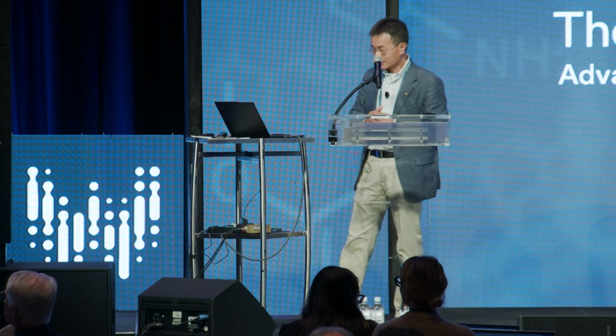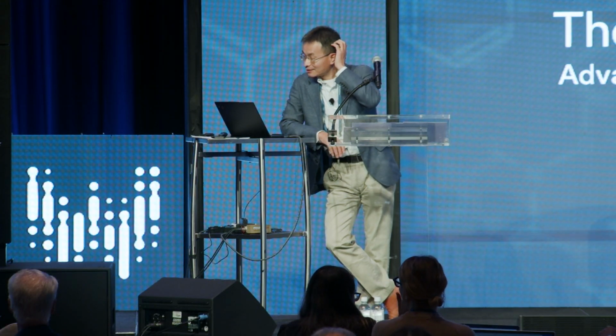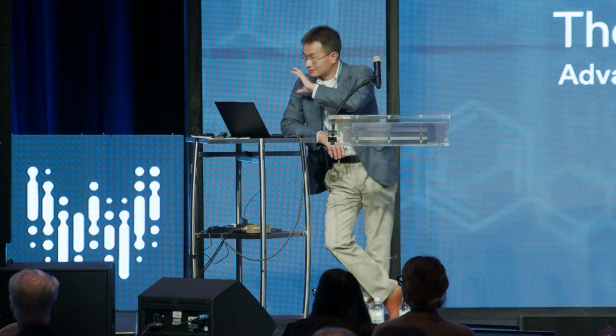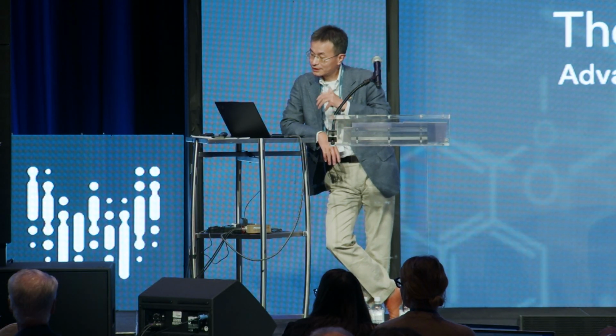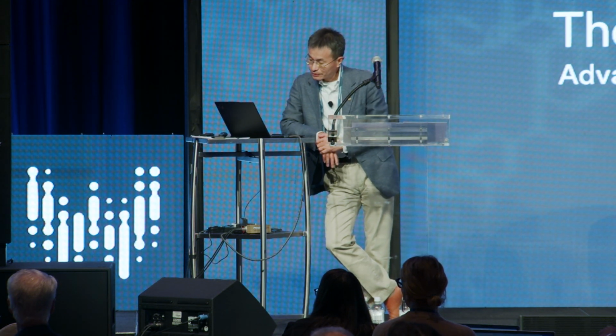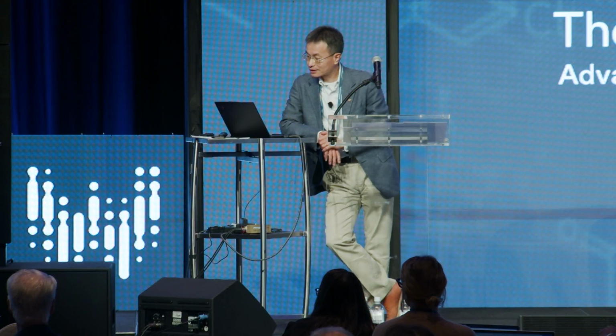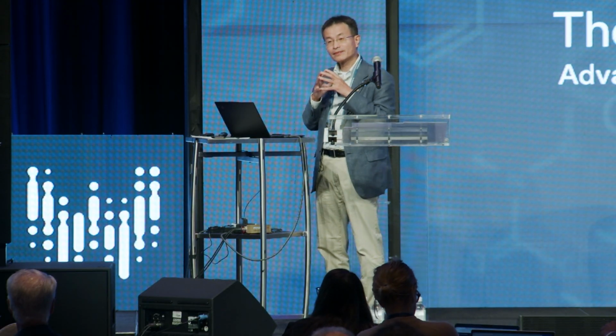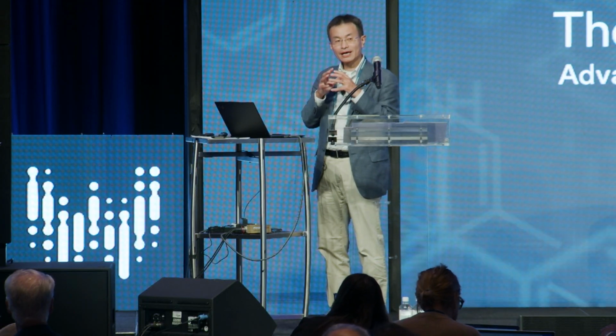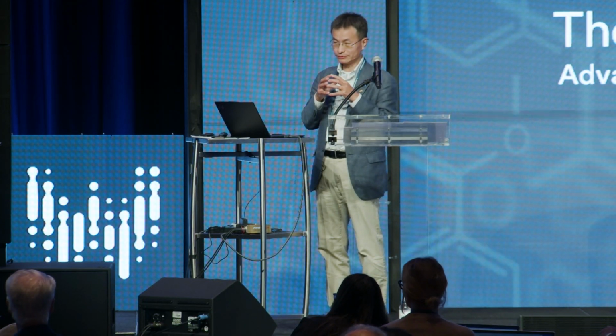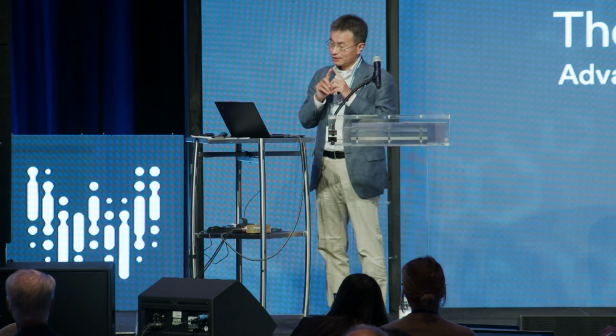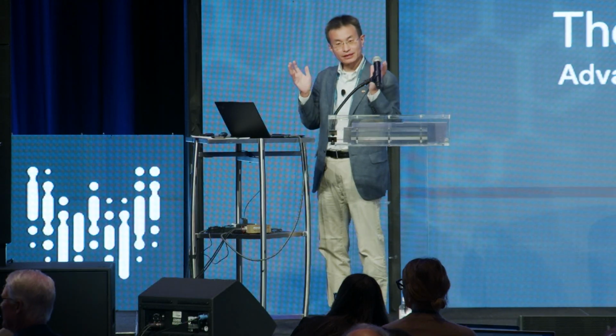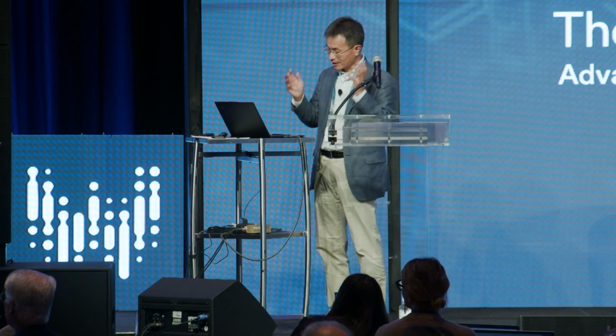Okay, so I finished my PhD at Harvard. I spent just very briefly 1 year at Santa Barbara with Galen Stucky. Then back in '99, I started my independent career at Berkeley, coming back with the entire group devoted to this area of VLS nanowire growth and their optoelectronic properties. And I think the first work we did is quite important. That underpins, for the first time, the growth mechanism, how we can have precise control in this one-dimensional nanostructure. That's the key. Before we have this precise control, we cannot talk about size-dependent properties. So that's the growth mechanism.